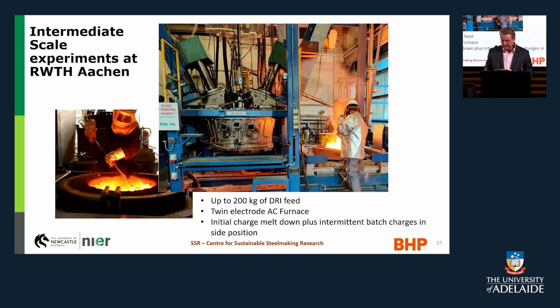And we've done some stuff at a little bit bigger scale. So in March this year, we spent a good month at Aachen University in Germany. As it turned out, we had made some hydrogen-reduced DRI in Frankfurt the year before. So we had some material left over, and we said, let's just try and smelt it in Germany because it's too hard to ship it back to Australia. So we took it there, and the Aachen journey was interesting. It's a twin electrode AC furnace, up to 200 kilogram type size. We learned some interesting things there and came away with a set of results.